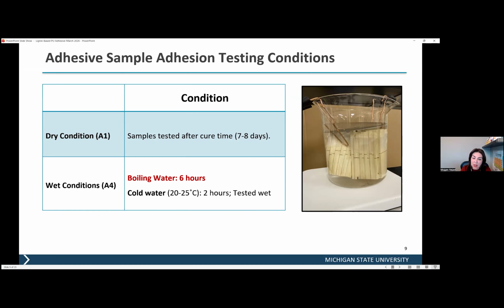And then wet adhesion is very rigorous testing. What they require is that we make the CLT sample similar to the samples that you see in this picture. We have to soak it in boiling water for 6 hours, then immediately remove it and put it in cold water for 2 hours, and test the adhesion right away after the cold water.